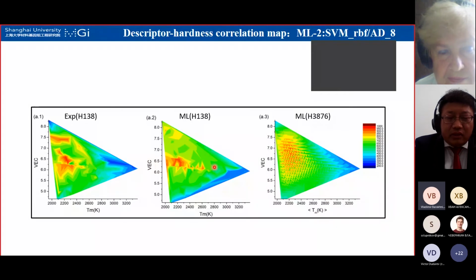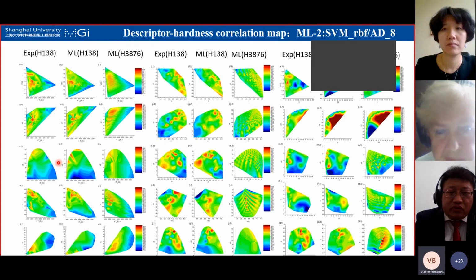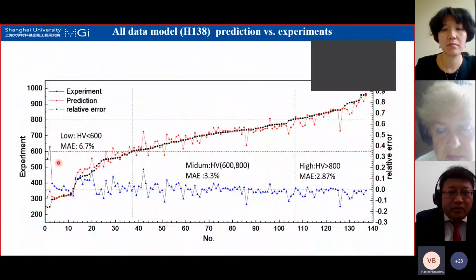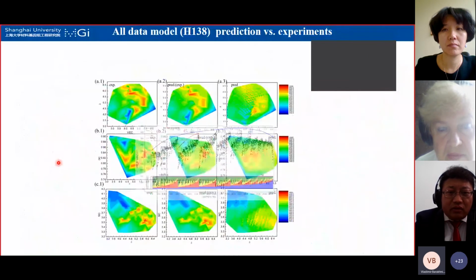In this experiment, the middle one is machine learning, and we use machine learning to predict all 3,876 compositions. They all look familiar and similar, and with such a map we can predict hard HEA materials very quickly, for example with a high melting point and medium valence electron concentration. We can do this for all possible combinations of the features we use. So by such a map, we can make very quick predictions for new alloys. The comparison between experiment and prediction agrees pretty well overall.